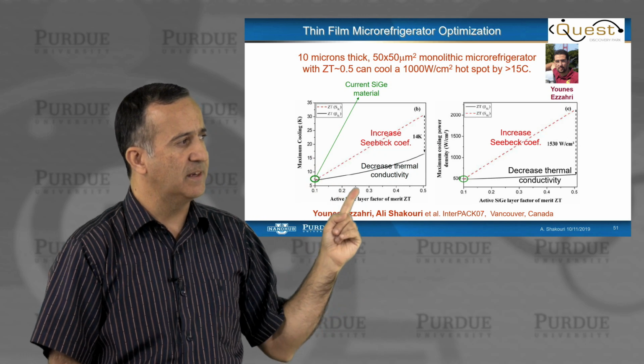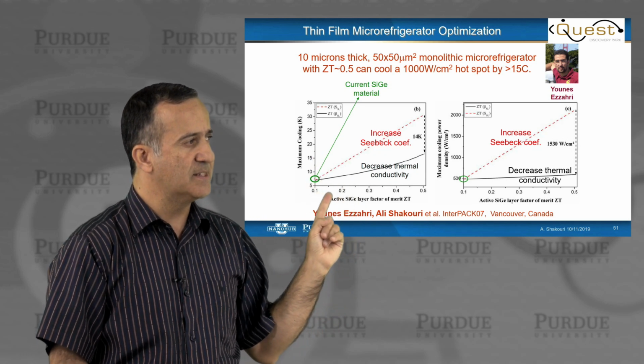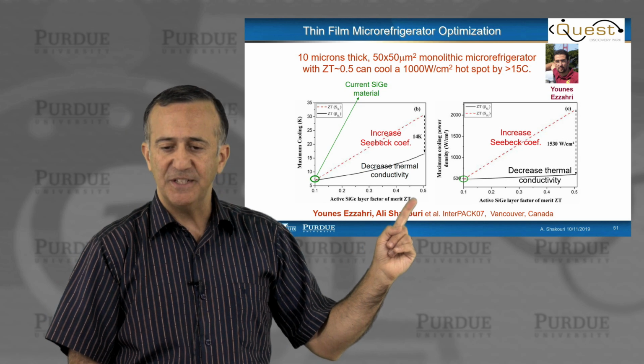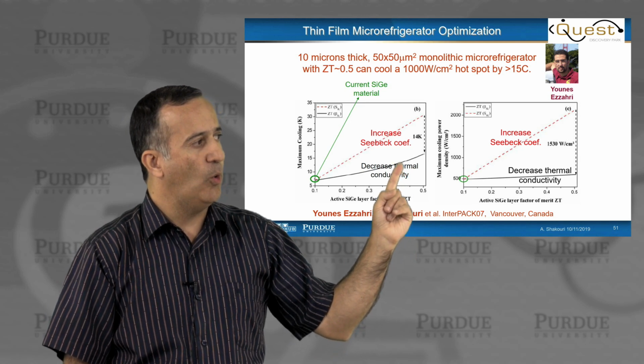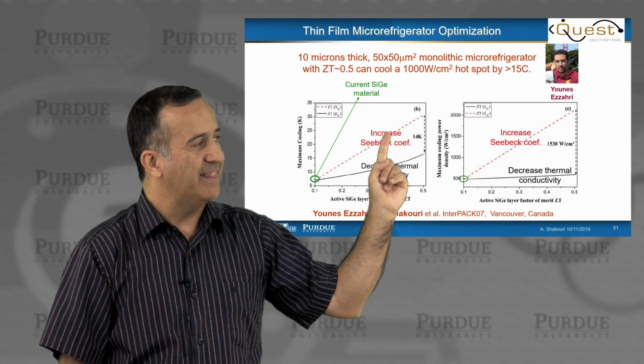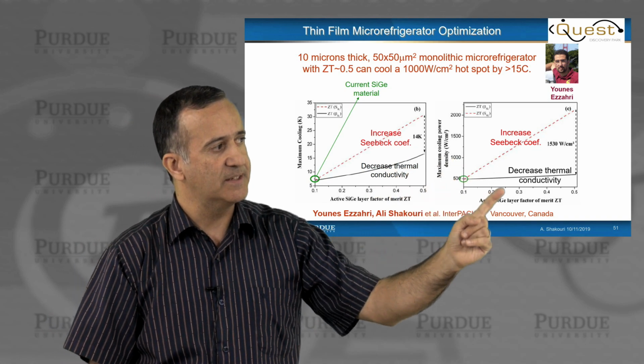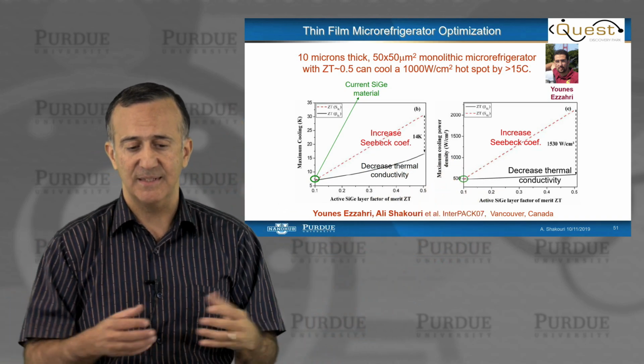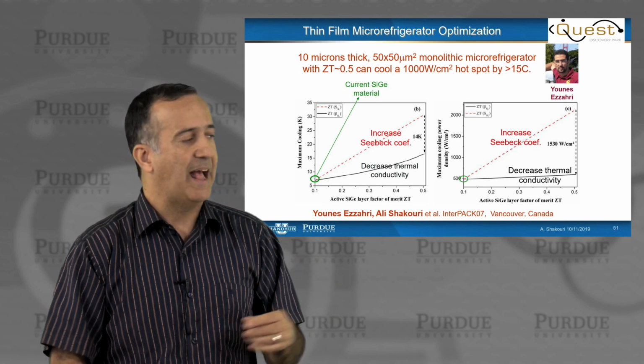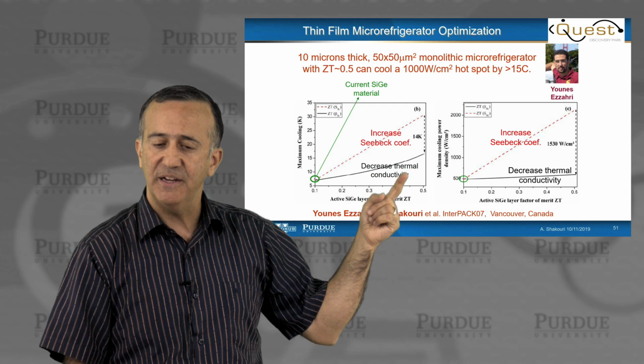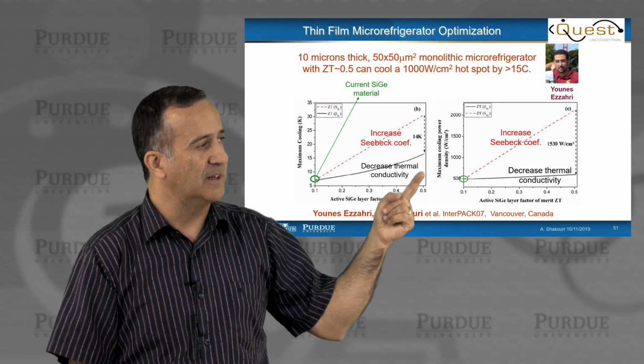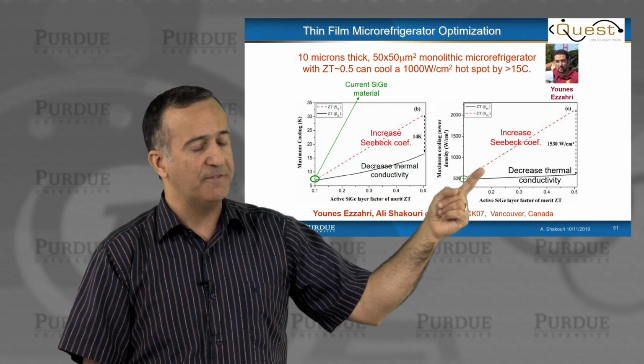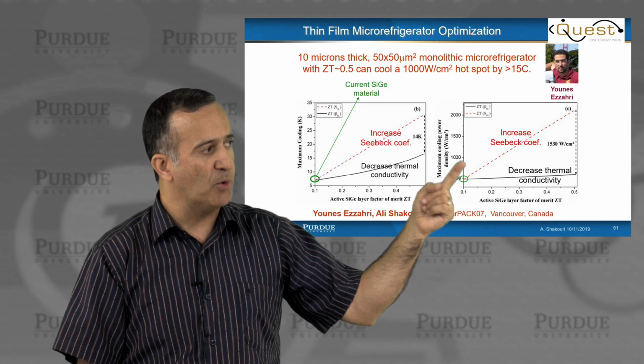What is interesting is that you can increase ZT either by reducing the thermal conductivity or by increasing the Seebeck, and the impact on the refrigerator is not the same. That means that ZT is not the only parameter. It's because of the parasitics that happen inside the device. And here we are talking about hotspot removal. Increasing the Seebeck coefficient or the power factor is more important.